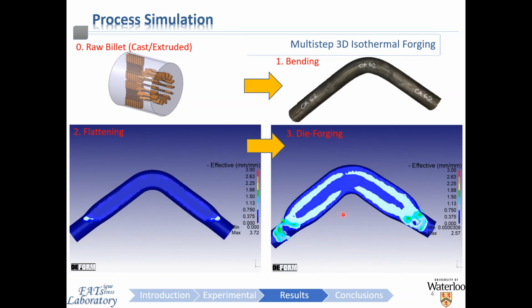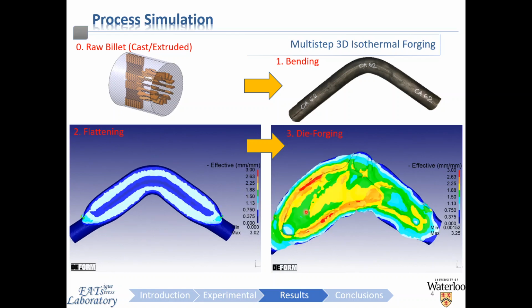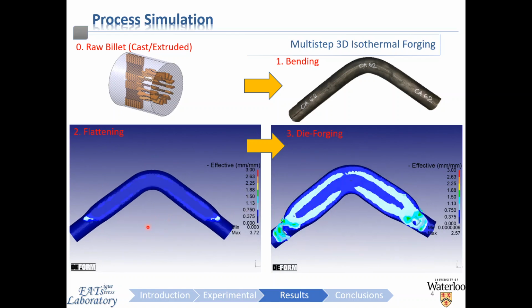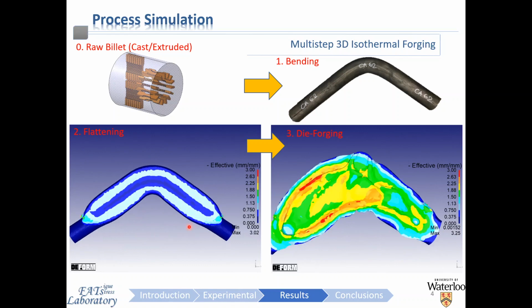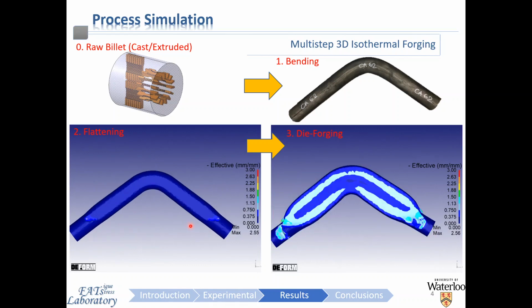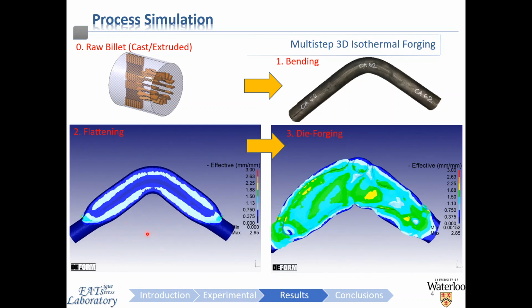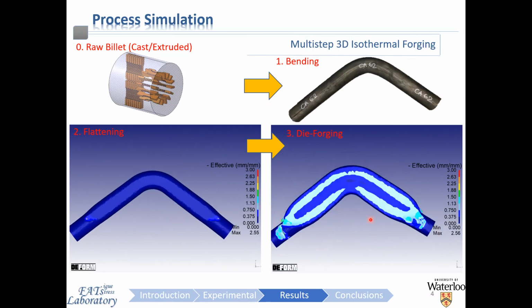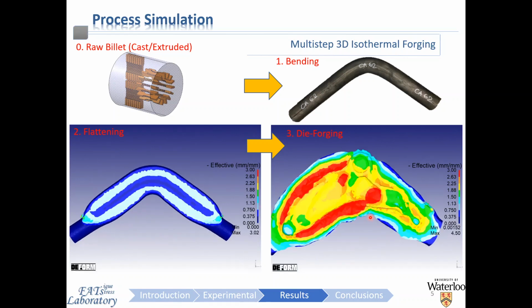In the animations you are seeing at the bottom here of the slide for steps 2 and 3, you can see the evolution of the effective strain being shown within the material for each step, and the fact that the strain of the final stage of step 2 is the initial condition for step 3 is an important thing to distinguish. You can see this more clearly highlighted here in these static images.